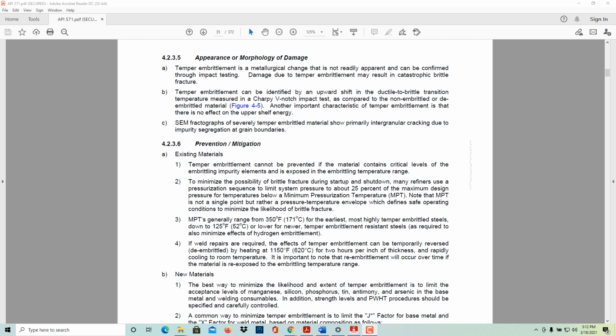See Figure 4-5. Another important characteristic of temper embrittlement is that there is no effect on the upper shelf energy. SEM fractographs of severely temper embrittled materials show primarily intergranular cracking due to impurity segregation at grain boundaries.